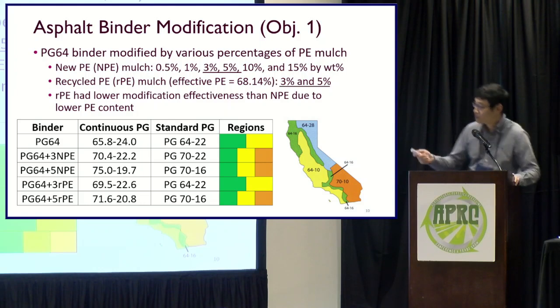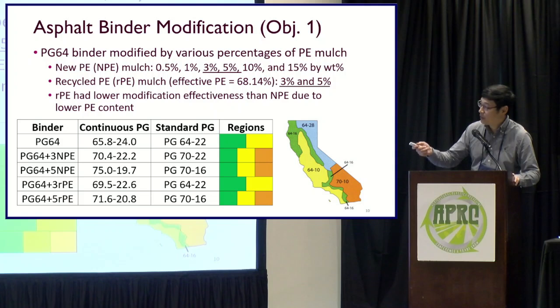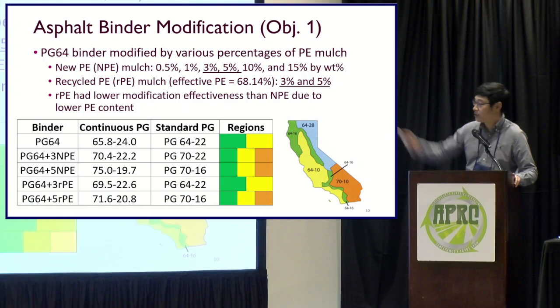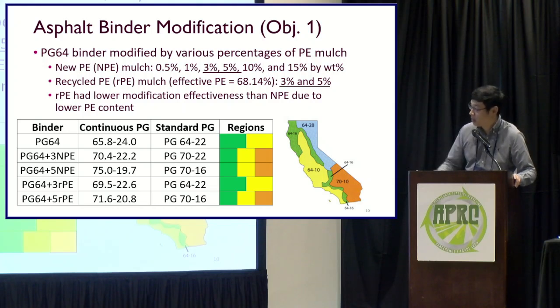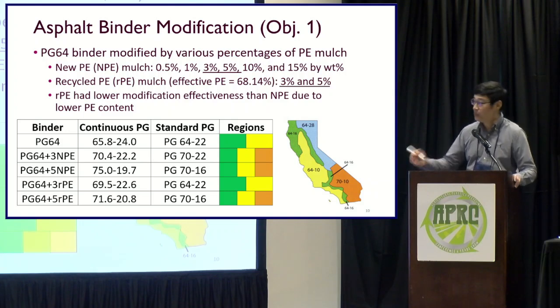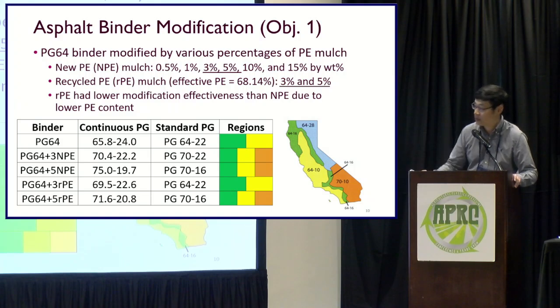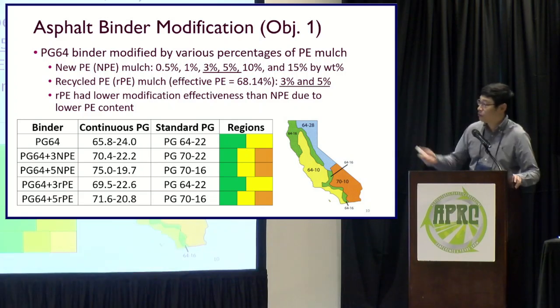If you look at there, when we have the PG 64 binder, it can only be used in the inland valley and also the north coast region, this green and yellow one. But if we add 3% or 5% plastic there, the PE, LDPE over there, actually we can extend the use of this binder to the desert area, to the PG 70 area. Same thing for the 5% recycled one, so we can extend the use of the binder in the desert area. And another conclusion from this study, when we have the recycled PE mulch, it has a lower modification effectiveness than the new PE mulch, mainly due to the lower PE content.